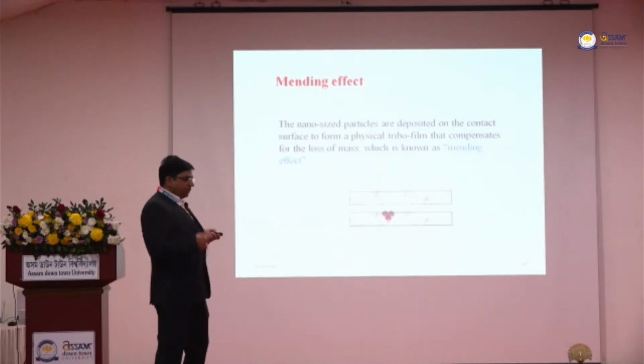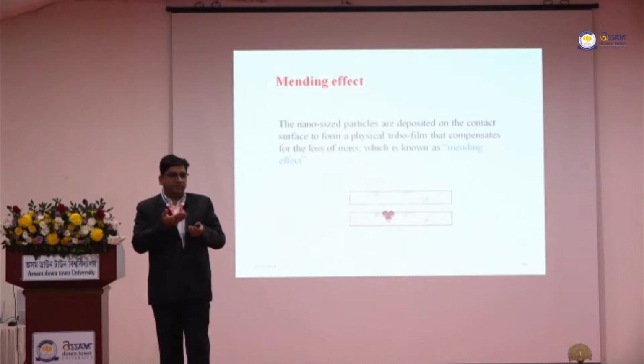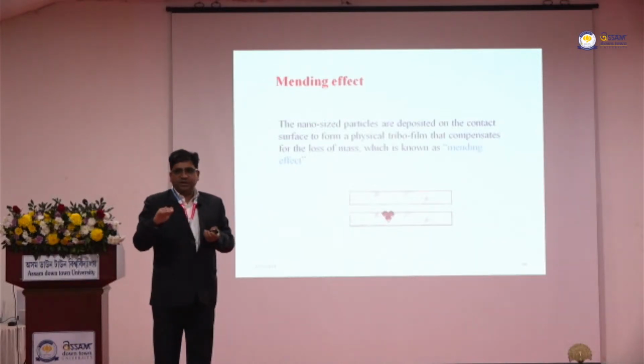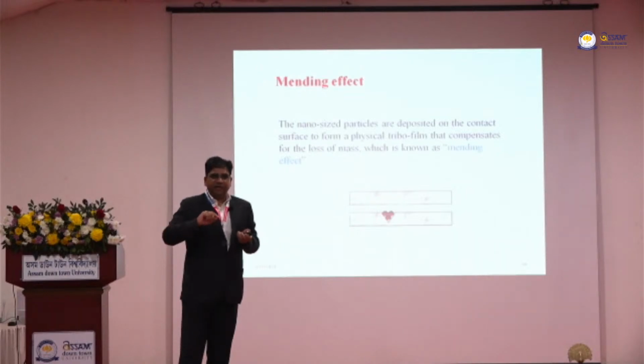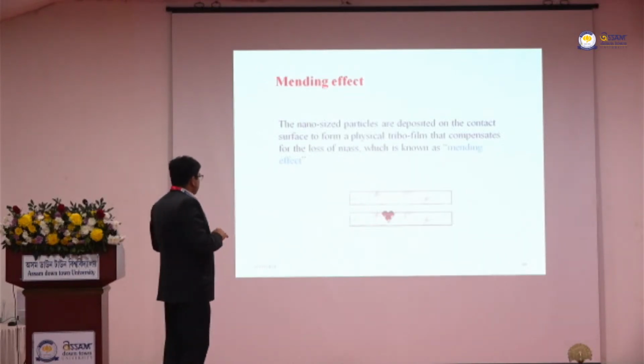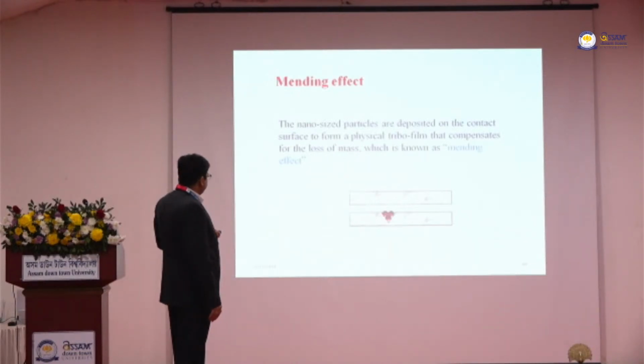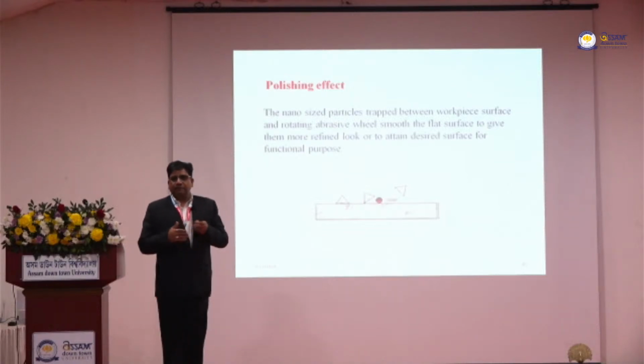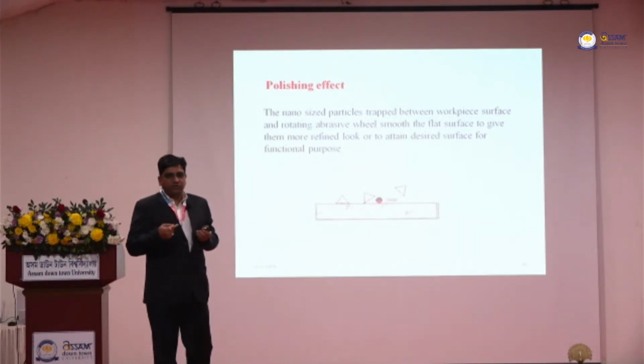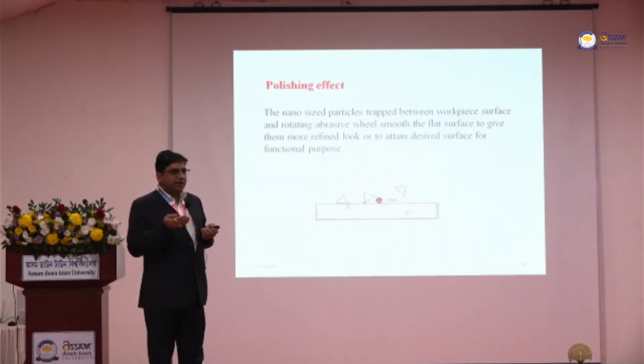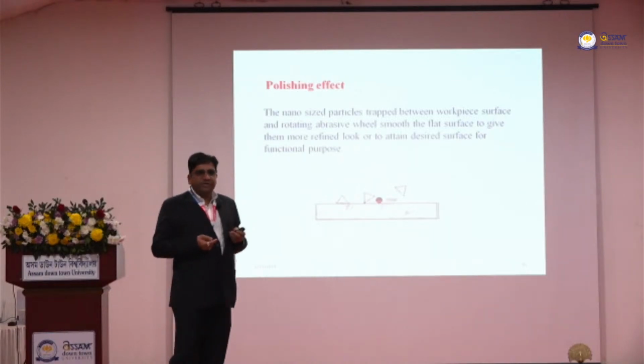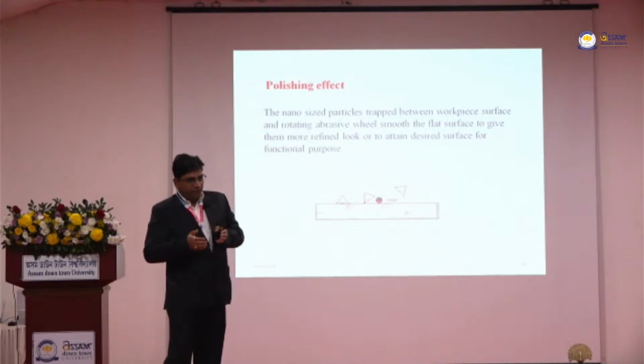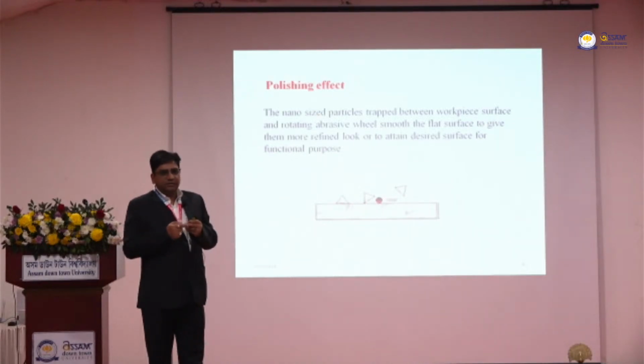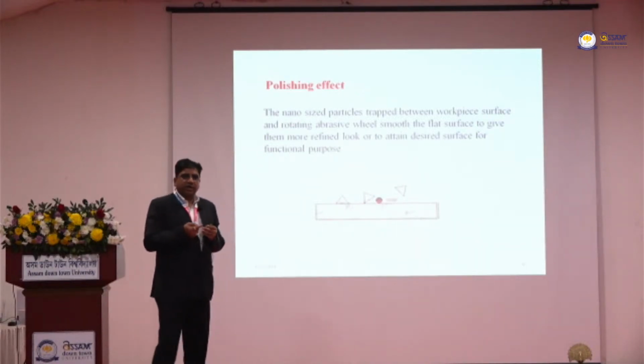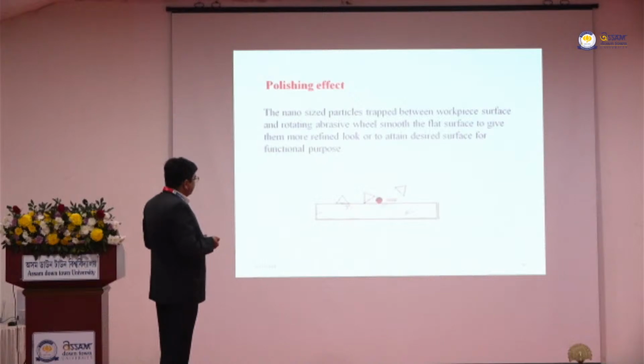So this is the mending effect. While doing machining operations, when you are peeling something or sliding something, the weaker zone can come out from the surface and make small pits. So the nanoparticles can be filled into that particular cavity of nano size, and they can create a flatter surface as compared to the rough surface. So it is the mending effect, and this is the polishing effect. If a number of rolling particles are there, they act like rubbing the surface with fine abrasives, so they create a little bit finer surface. So these are the surface enhancement effects. So by adding nanoparticles into the cutting fluid, we got a better cutting fluid with higher thermophysical properties, and it created better results.